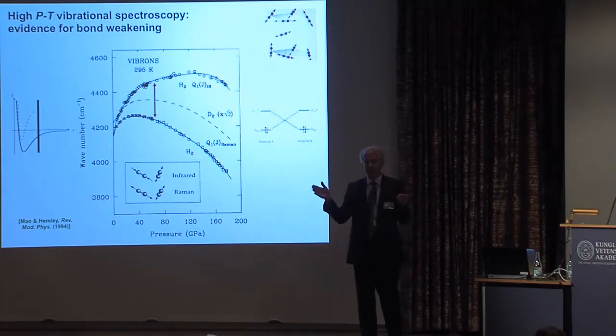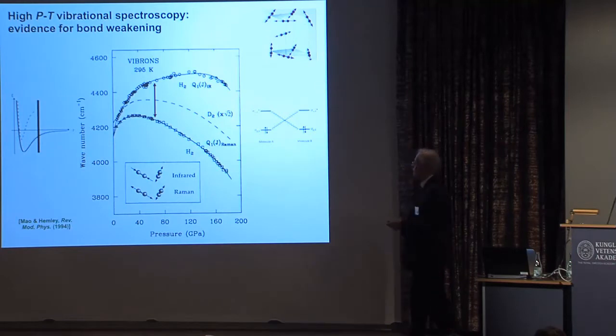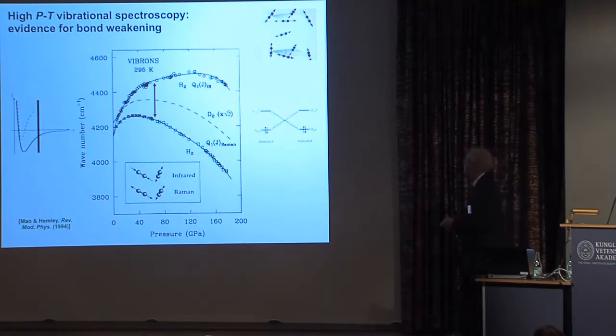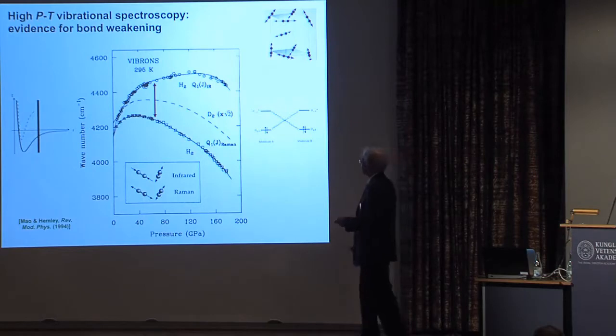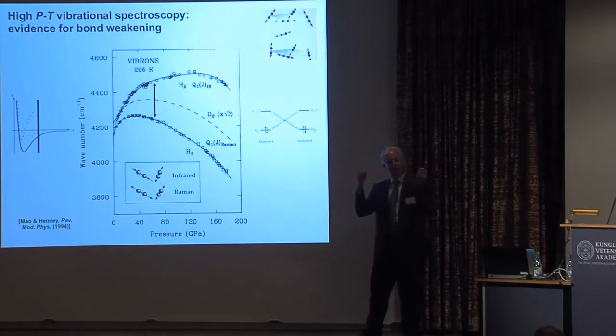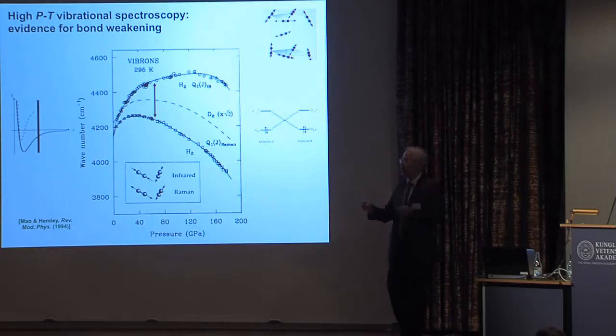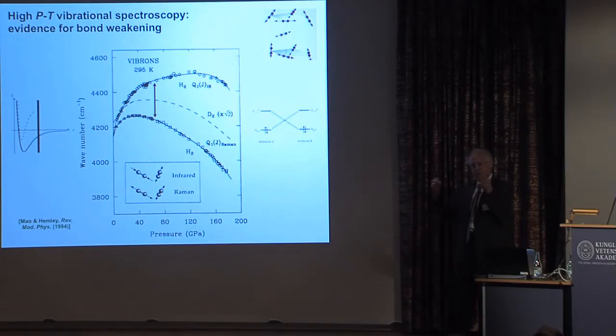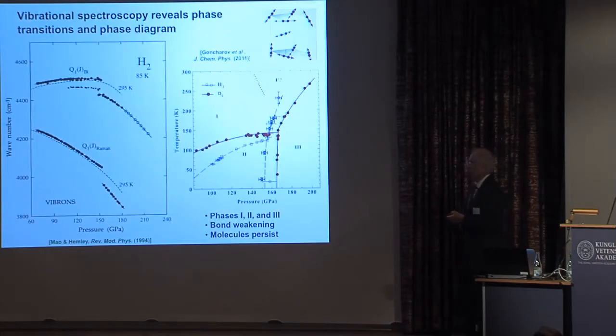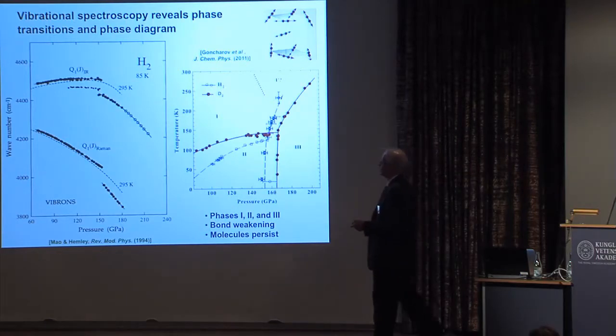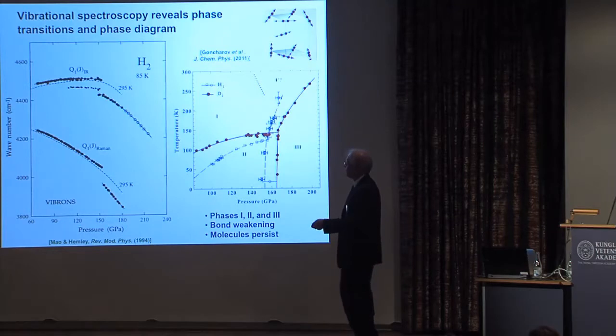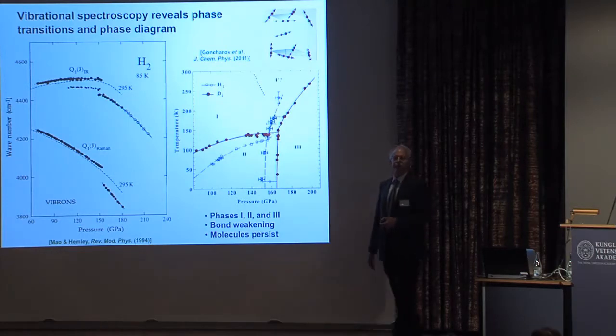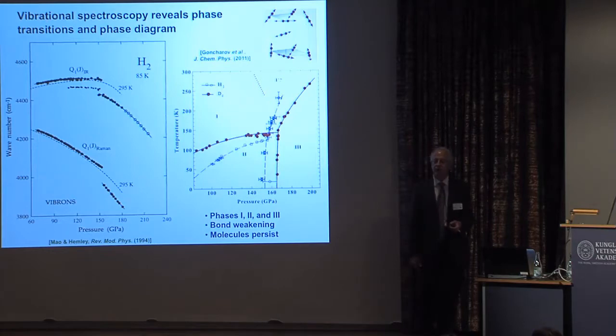Here we're looking at the frequency shifts of the intramolecular mode probed by both Raman and infrared. And in the HCP structure, the infrared mode is formally forbidden because there's no dipole, but it has some weak activity due to these intramolecular-intermolecular interactions. Well, if one does this as a function of temperature, one can see more. You can see this increase in frequency and the decline, but you can also see these breaks, discontinuities in the vibrational frequencies.